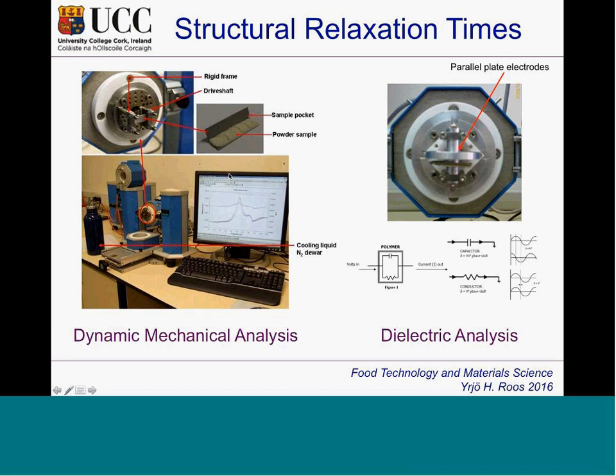We can see typical loss modulus curves or tan delta curves, and we can also use dielectric measurements. This is a parallel plate arrangement, where you place a sample between the plates. It becomes a conducting material, and we can get similar type data as one gets from DMA, but on the dielectric properties.